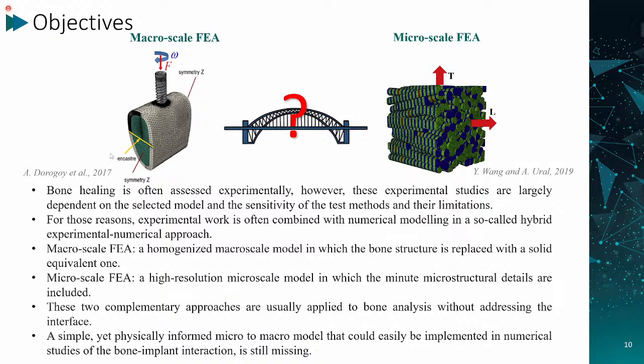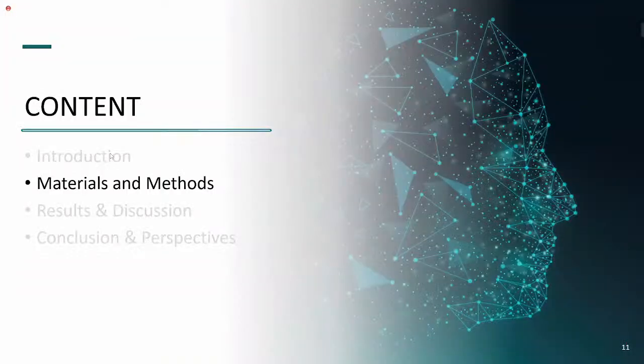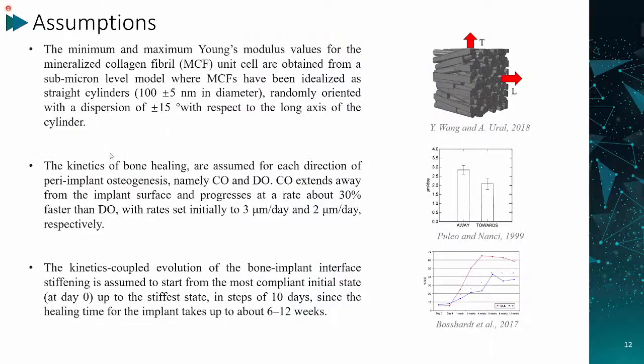Next are the materials. Before creating the model, we have to make a few assumptions to simplify the modeling work. So assumption 1: the minimum and the maximum Young's modulus values for the mineralized collagen fiber, MCF, unit cell are obtained from a submicron level model, where MCFs have been idealized as straight cylinders. These cylinders have a diameter of 100 plus or minus 5 nanometers, and are randomly oriented with a dispersion of plus or minus 15 degrees with respect to the long axis of the cylinder.